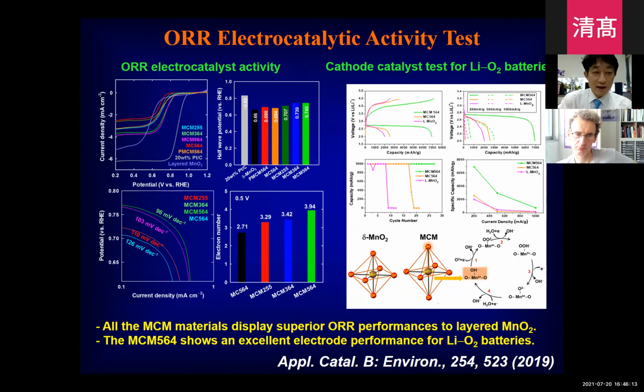So we apply those materials as an oxygen reduction electrocatalyst, as you can see here. We can confirm the enhancement of ORR catalyst activity. We also apply those materials as a cathode catalyst for a lithium-oxygen battery, as you can see here. The hybrid material shows much better performance as an electrode for the lithium-oxygen battery compared with the manganese oxide nanosheet.